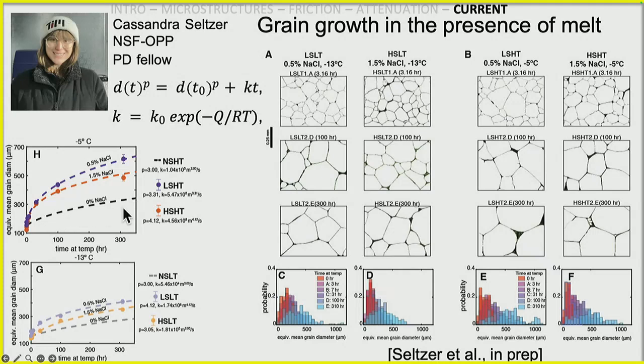The cut to the chase is that with a little bit of melted saline in the grain boundaries, they become much more mobile. The grain boundaries move, and you can grow your grains much faster. But too much of a good thing can slow it down. So if you get to a higher concentration, she actually saw a decrease. The orange has more saline than the purple at the two temperatures she looked at. So it seems like a little bit helps, but then the salt just kind of gets in the way.